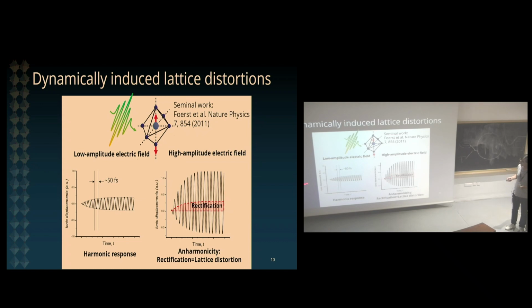So what we would like to do is not to have an ionic displacement that oscillates harmonically and then decays back, but we would like some oscillations along a displaced zero. All right? And this phenomenon can occur. It was initially discussed in this seminal work. It was, for the very first time, discussed much earlier, maybe in the 50s, 60s, in the literature of Raman scattering. So this is known as nonlinear phononics, or as ionic Raman scattering.